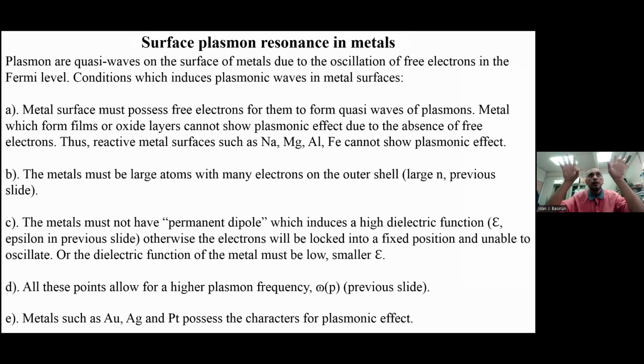Only metals which are inert, like gold, work. Gold is the best substrate to observe SERS and also to observe the plasmonic wave. In gold, all the electrons are on the Fermi level, and the gold surface is inert, meaning it does not bond with the oxygen in the air or the water moisture in the air. That's why you can observe plasmonic wave on the gold surface, especially when the gold is in nanoparticle form. Also silver surface: silver is basically inert. As long as silver does not form a bond with the oxygen or the water moisture in the air, you can observe plasmonic wave.